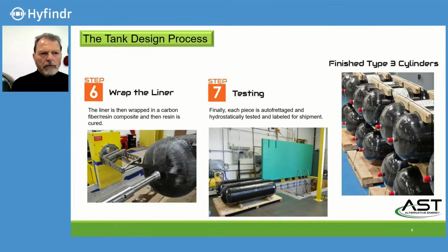Further on, we go to wrap the cylinder. So we do carbon fiber wrapping, and we use a wet process. There's wet and dry. The dry process is with pre-preg fiber. We use the wet process, which is probably the one most used in the market. And then we do the testing at the end. Every cylinder before it leaves the factory is tested 100%, which is the autofrettage and the hydro testing.